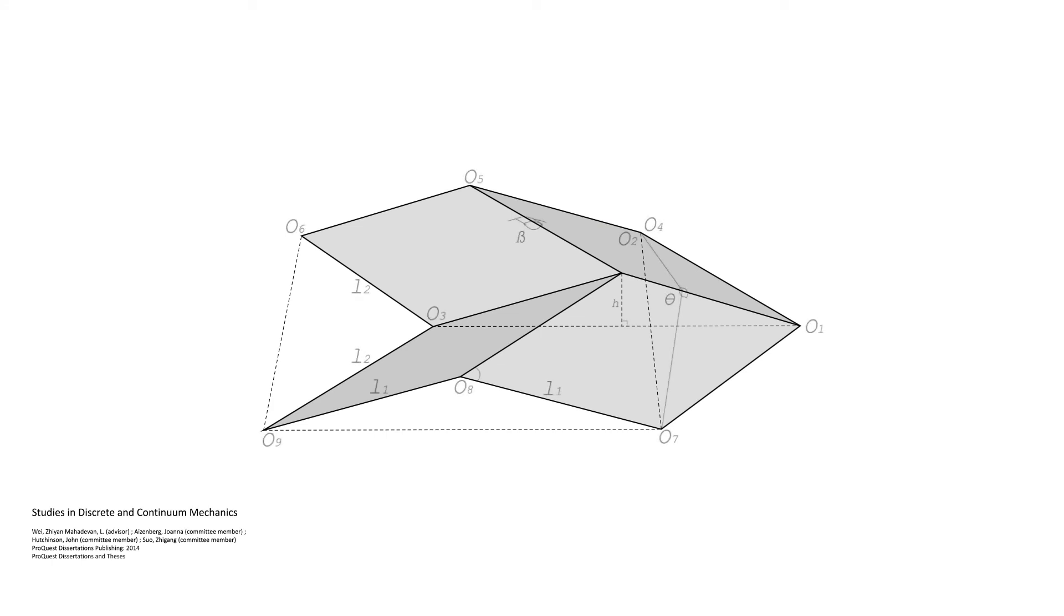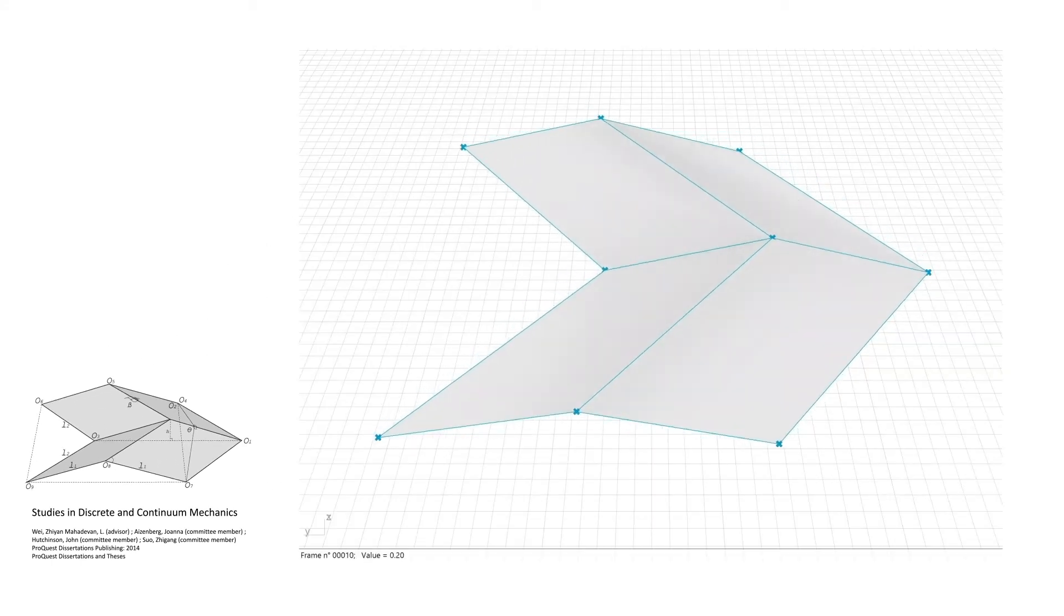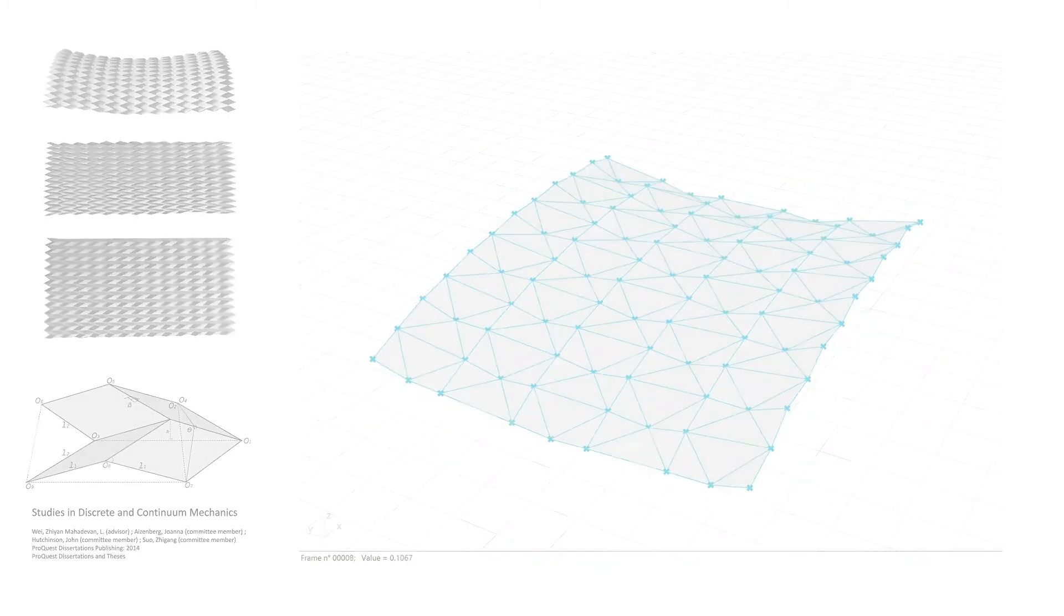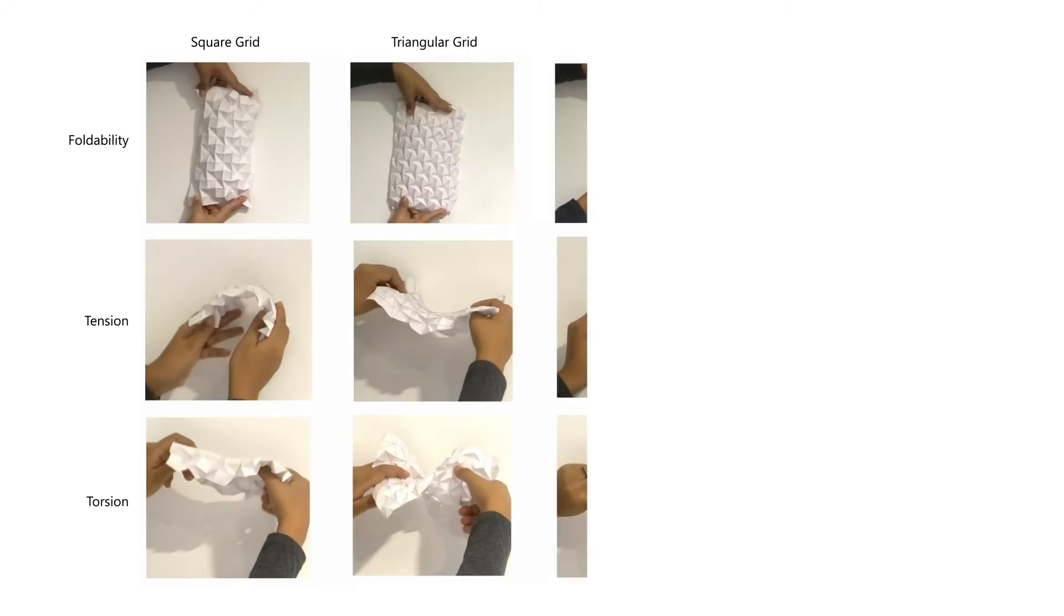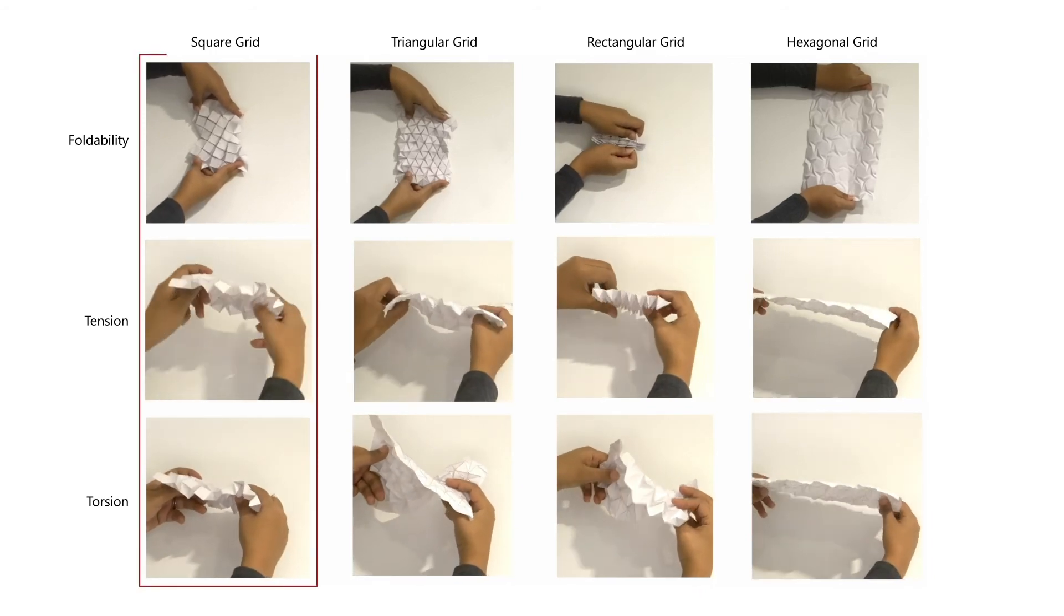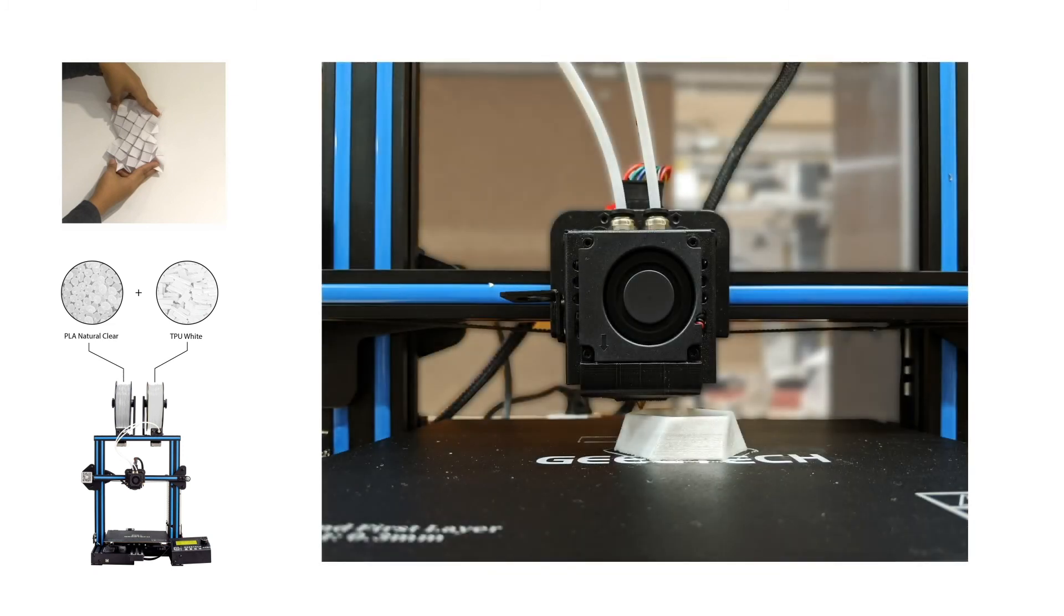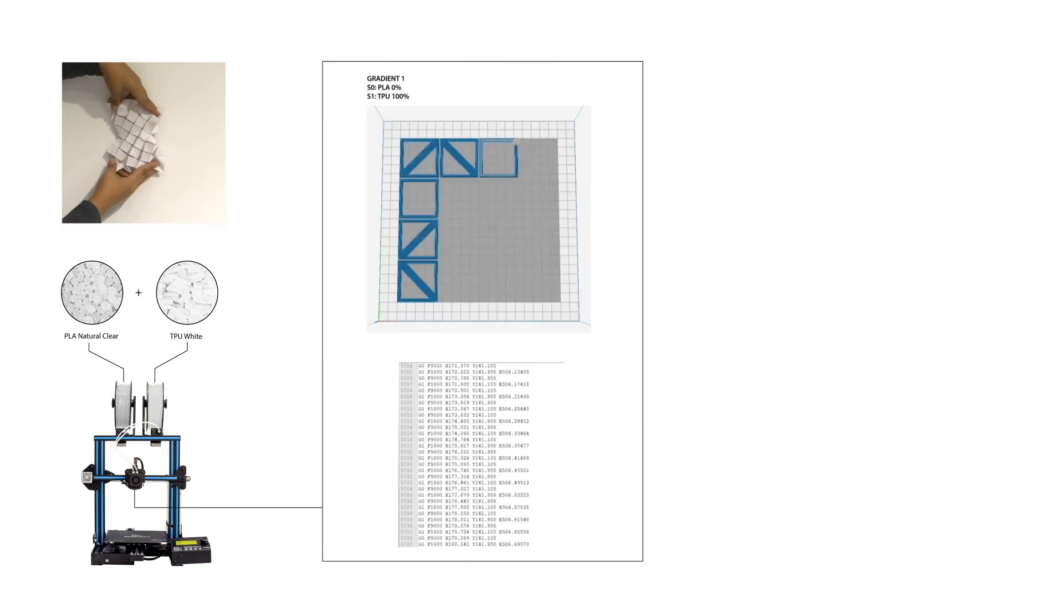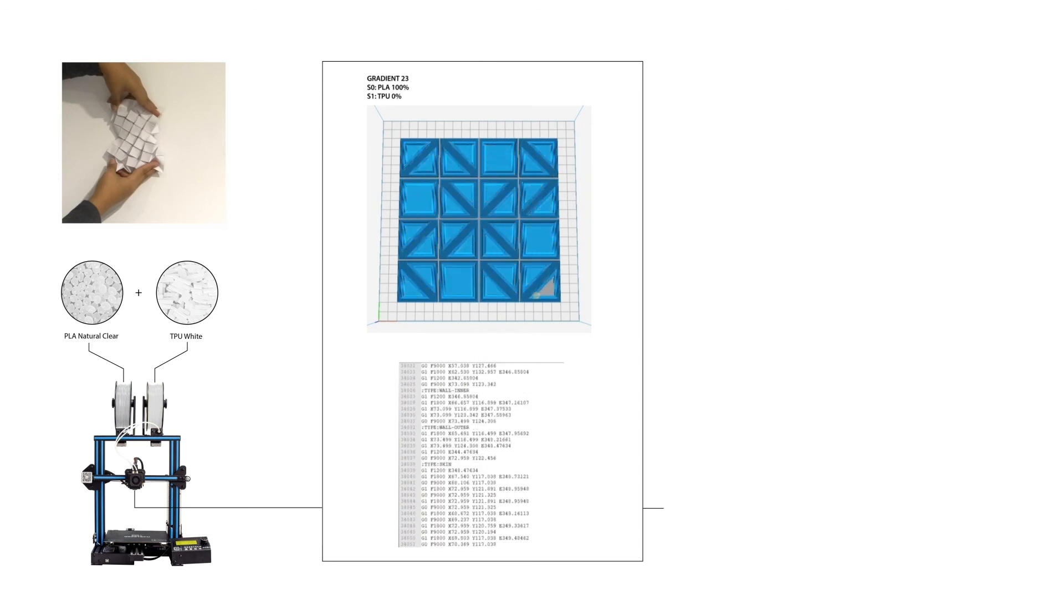In order to provide a continuous element with structural properties, the project makes use of a geometrical folding pattern capable of distributing structural efforts uniformly through a surface. Multiple patterns were tested in physical samples to evaluate their behavior under tension, compression, bending, and torsion, resulting with the quad-based grid as the most efficient pattern. Based on this pattern, we fabricated a foldable panel using a multi-material 3D printer with a dual extruder and single nozzle. The mixing ratios between PLA and TPU are controlled through the G-code to achieve gradient printing, which allows foldability.